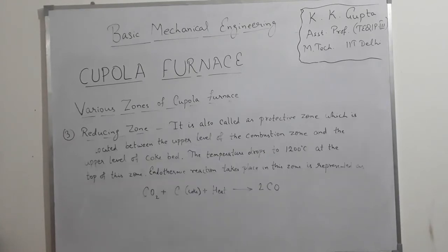Third zone is reducing zone. It is also called as protective zone, which is located between the upper level of the combustion zone and the upper level of coke bed. The temperature drops to 1200 degrees Celsius at the top of this zone. Endothermic reaction takes place in this zone, represented as carbon dioxide plus coke plus heat will give carbon monoxide. Since endothermic reaction takes place in this zone, the temperature decreases from 1800 to around 1200 degrees at the top of this zone. Combustion zone plus reducing zone is also known as superheating zone.